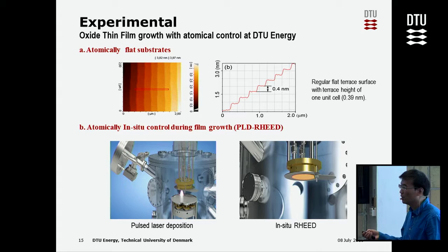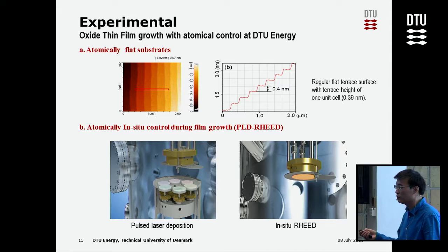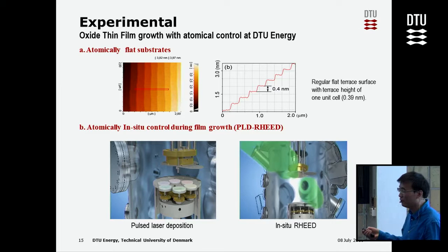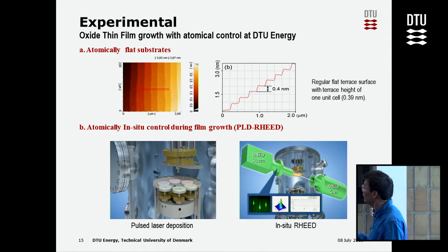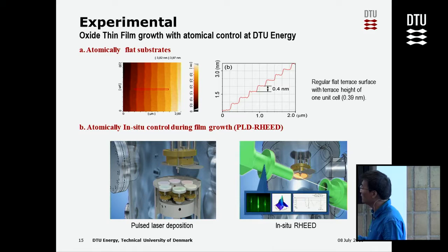We use a technique called pulsed laser deposition. Compared to semiconductor technology this is a relatively simple technique: you use a laser to heat a target inside a vacuum chamber, and there will be a plume. This plume is the material you want to grow, and it deposits on the substrate.